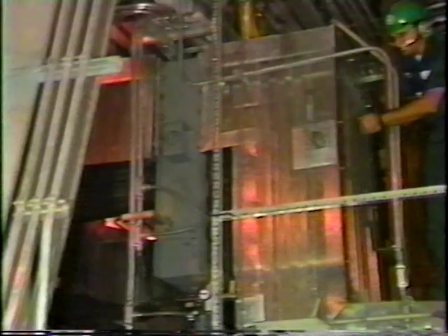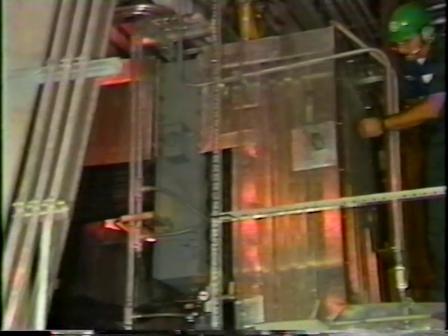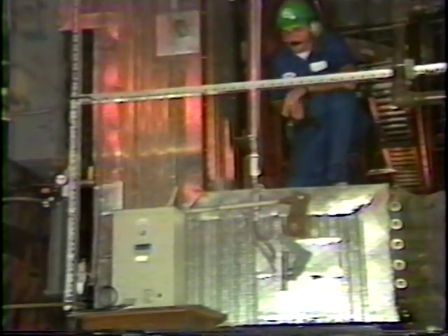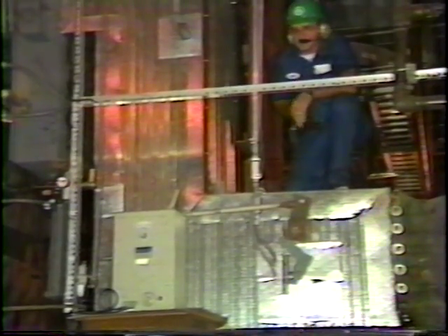Tempering air is provided to maintain constant air temperatures to the coal pulverizers. Temperature sensing devices are provided at the outlet of each coal pulverizer's fan. These devices regulate automatic dampers, which allow sufficient tempering air in to maintain primary air temperatures at the established set point of 150-degree exit temperature. Shown here is the positive air shutoff valve, which is located next to an airfoil. The basis of the measurement of airflow is the differential pressure across this airfoil, and it controls the airflow damper.